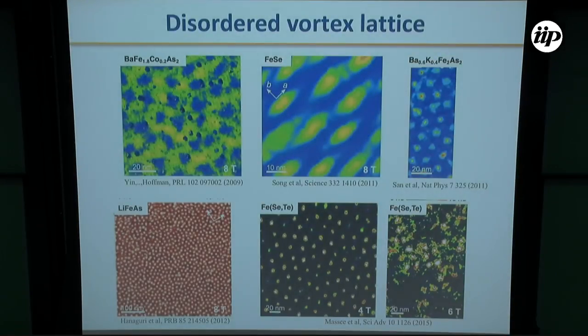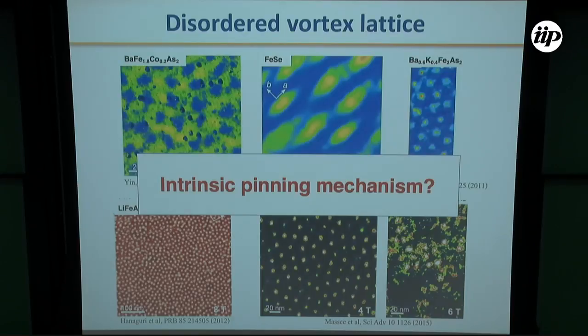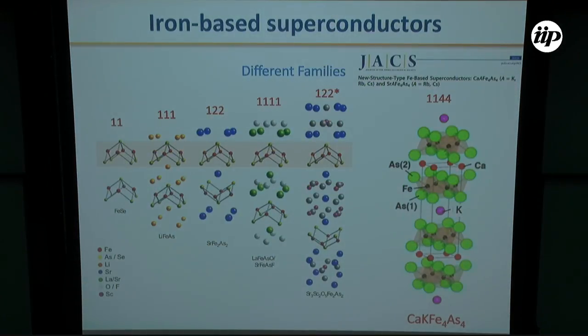The vortex lattice has also been studied in these materials, and here I show different STM images of the vortex lattice made in different materials and by different groups. The common feature is that the vortex lattice often appears very disordered, but still we don't have a clear correlation between the disorder in the vortex lattice and the pinning landscape. Again, in these materials, the vortex lattice has been studied in the presence of substitutional disorder in doped compounds. So again, it would be nice to study the disorder in the vortex lattice in a stoichiometric material in the absence of this substitutional disorder. So this is the main motivation of the talk.